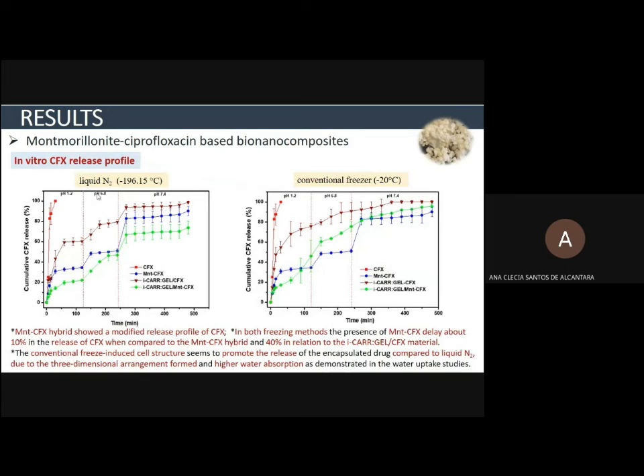And finally, the in vitro ciprofloxacin release profile was investigated. The cumulative percentage of ciprofloxacin released as a function of time was determined by in vitro drug release assays, where the bionanocomposite beads frozen by conventional freezing or liquid nitrogen were kept in contact with simulated stomach and intestinal fluids at different pH values for around 8 hours in order to simulate the different steps of the gastrointestinal tract as an in vivo process. For comparison purposes, ciprofloxacin pressed as a tablet was also investigated.